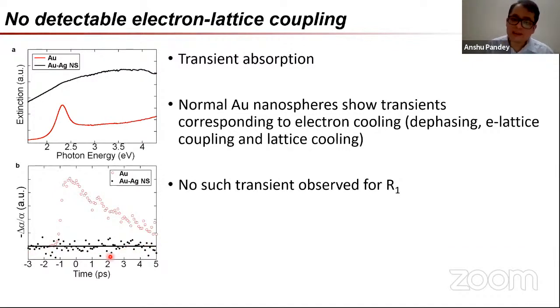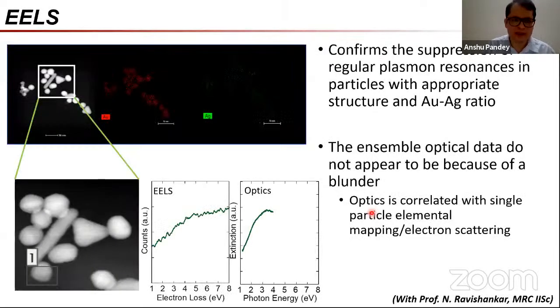So it appears that either it does not interact with light at all, or if it does interact with light, then somehow the electronic motions are totally decoupled from the lattice. So we get no such transient for it. And this also gets very, very strange. If we look at EELS, we find that these sort of things are actually mirrored in EELS.